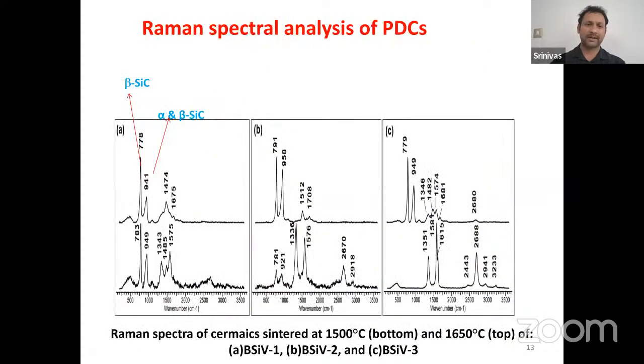In the Raman spectrum also, you see the D and G bands. On the left side, 778 and 941 are of SiC formation. We already know there is no SiC formation at 900; here the lower one is 1500 and the upper one is 1650, where SiC occurrence can be found from the Raman spectrum too. So all this spectroscopy shows that SiC formation is initiated at 1500 degrees centigrade and completely converted at 1650 degrees heat treatment for this polymer.